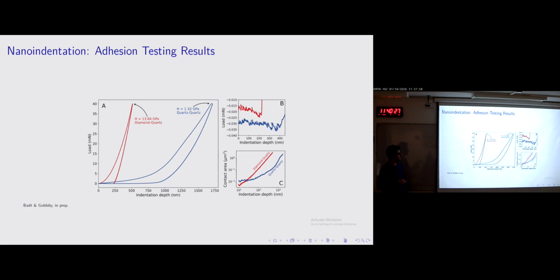Let's start with the diamond on quartz. We're starting at 0. This is the load on the y-axis and indentation depth on the x-axis. You can see we're loading up the sample to a prescribed load, 40 millinewtons, and that means at the peak we have a contact pressure of about 13.8 gigapascals. Okay? The diamond is really, really stiff, it doesn't deform, and we can really get to high stresses.